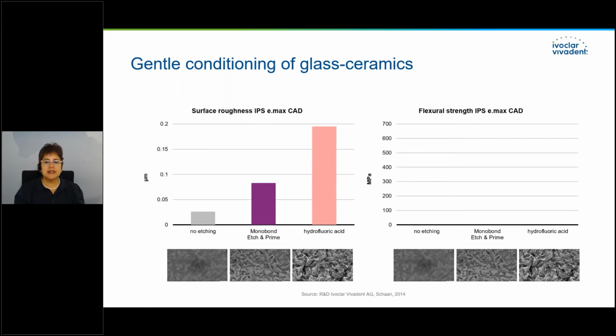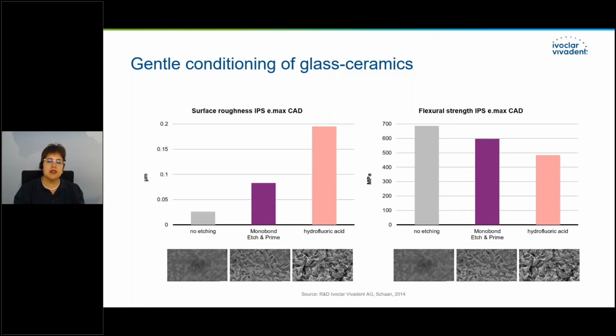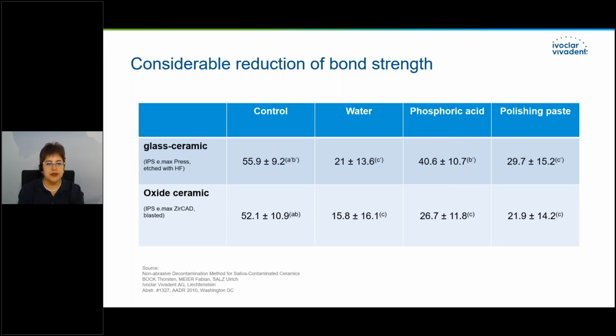Compared to hydrofluoric acid, Monobond Etch and Prime conditions the ceramic surface much more gently. That means that you will not weaken the glass ceramic. The surface pre-treated with Monobond Etch and Prime shows less than 50% of the roughness of the surface etched with hydrofluoric acid. Therefore, the effect on the flexural strength of the glass ceramic is less pronounced, and it is conditioning more gently.